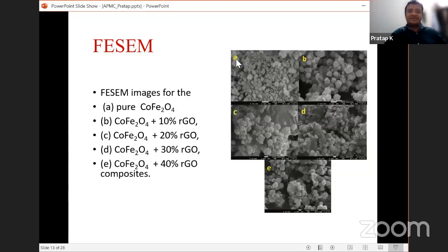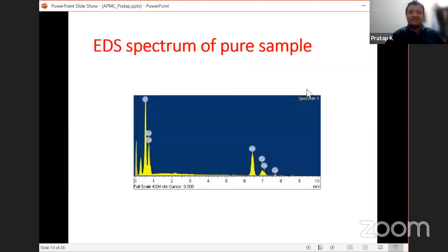Now, these are our SEM images. If you look into the SEM images, this is pure cobalt ferrite, 10% RGO with cobalt ferrite, 20% RGO with cobalt ferrite, 30% RGO with cobalt ferrite, and 40% RGO with cobalt ferrite. You can see that they are spherical particles, and this is the graphene layer. They are anchored onto the graphene layer. So this is how the morphology looks. And when you take the EDS of the sample, you see Fe, Co, and O. So there are no impurities and the sample is formed in a pure form.